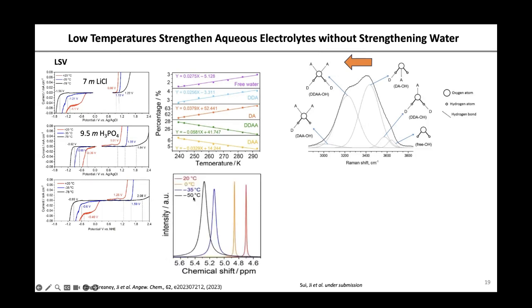Now, we also tested the NMR, right? The NMR also tells us that by lowering the temperature, you're going to have a downfield shift. That is about de-shielding of hydrogen nuclei. De-shielding means you have less electron density around protons, around hydrogen. That is also about a lowered bond enthalpy. So how come, right? How come you can have weakened water molecules, but you have the aqueous solution voltage window dramatically increased? So now we have to look at the entire equation.